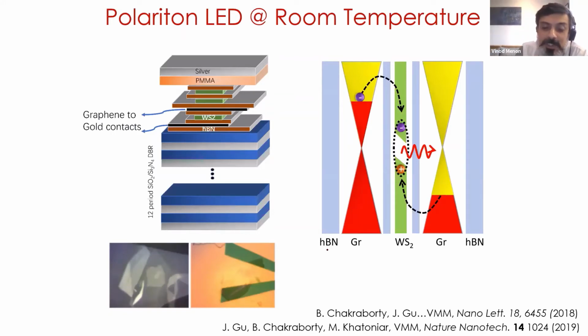So what is shown here is a device that is made fully with the Scotch tape exfoliation technique. It starts with a hexagonal boron nitride. You stack a layer of graphene, a thin layer of hexagonal boron nitride, tungsten sulfide, another layer of hexagonal boron nitride, graphene, hexagonal boron nitride. If you stack these things up, then the band structure of this material looks like this.